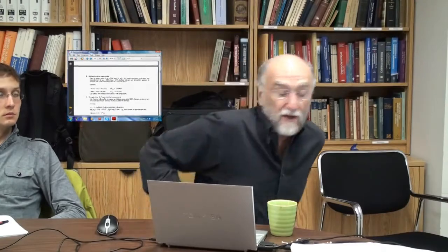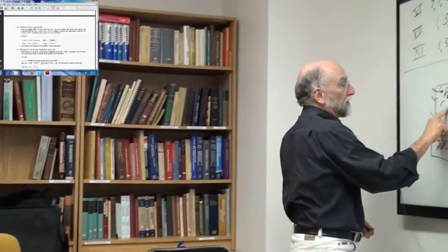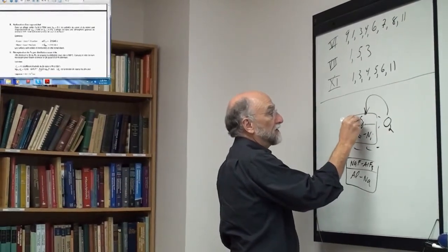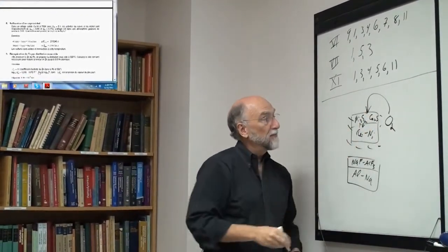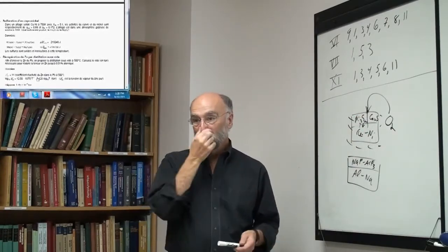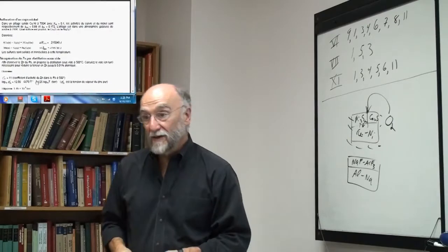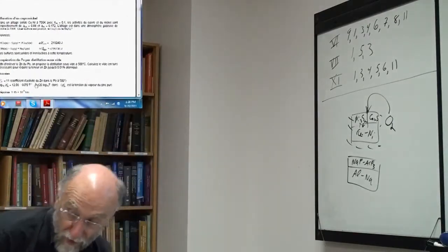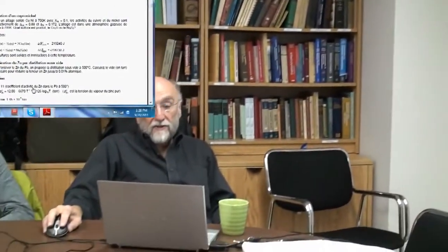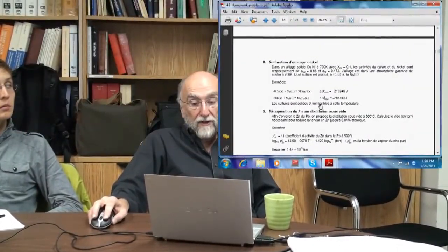Okay, so then just to prove a point, number 8 was again the same thing. This is sulfidation of nickel, so it's the same as here, except here we had cobalt nickel, now we have copper nickel. And now the difference though is here you have nickel sulfide and copper sulfide, but they are not miscible. They form two different phases. It's either one or the other. And now you don't get both, you get one or the other. The sulfides are solid and immiscible at this temperature.